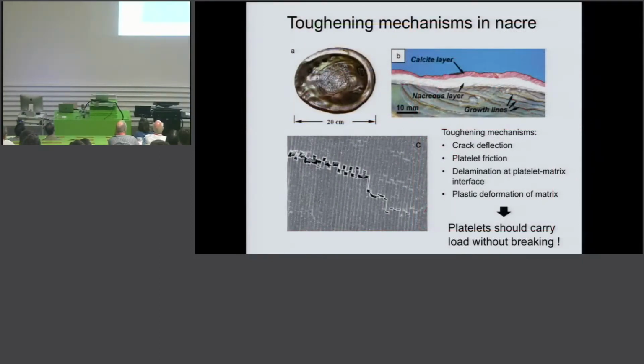All right, so what happens if we now try to break this material? If a crack starts propagating through the structure, and the structure is designed in such a way that the platelets are always aligned parallel to the surface of the shell. So if you try to bend it, you would have a crack going this way, perpendicular to the direction of the platelets. And what you find is that this crack has a very hard time going through the material. And that is because it is always deflected whenever it finds a platelet.